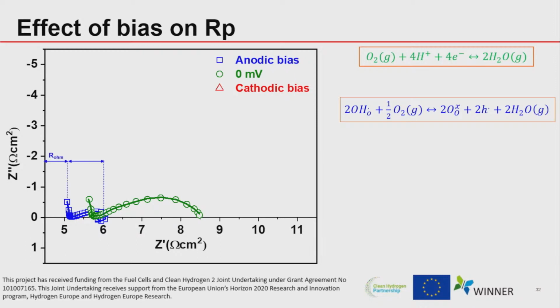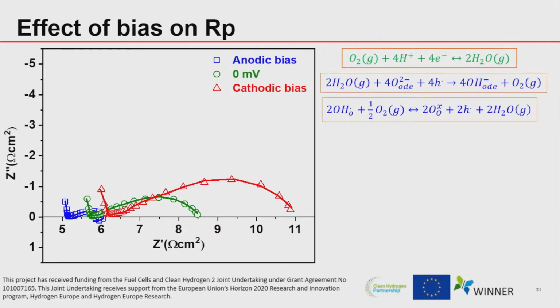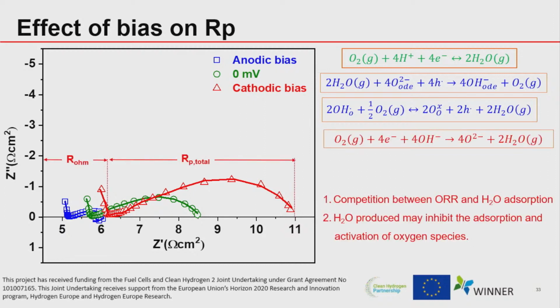The reason being, when you have applied anodic bias, that is a positive bias, you have increased the pO2, hence you have introduced some hole conduction into the system. It is not a short circuit, but there is some p-type or electronic conductivity in the electrolyte, and the R ohmic has decreased. Now, if I apply cathodic bias, what I see is that the resistance has increased. So this indicates that the material works best in anodic bias, but not so much in cathodic bias.